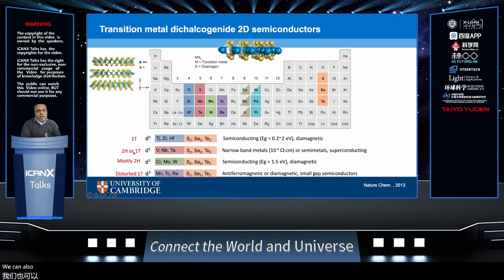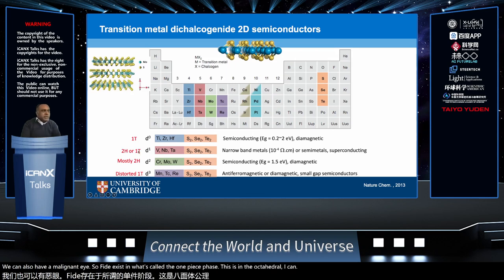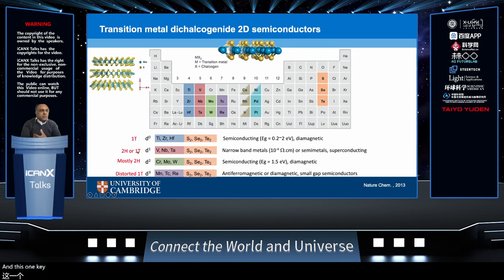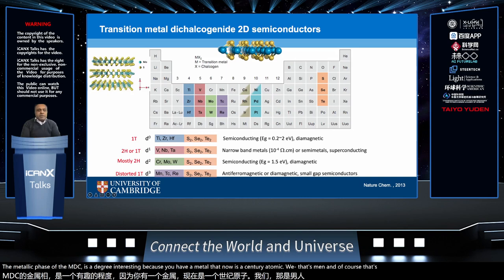We can also have molybdenum disulfide exist in what's called the 1T phase. This is in the octahedral configuration, and this 1T phase is metallic. We've utilized chemistry in our group over the last dozen years or so to go between the semiconducting and metallic phase. The metallic phase of these TMDCs is particularly interesting because you have a metal that is essentially atomically thin. And of course, that's fundamentally a difficult thing to do.